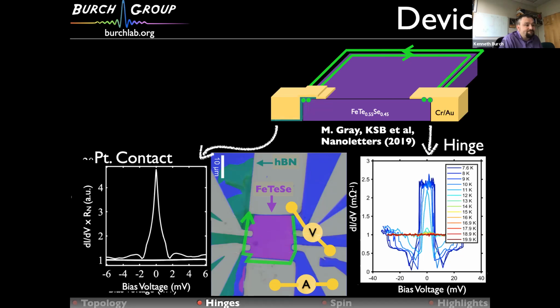But the temperature range is the same as before, right? Previously, the problem whenever you do these transport measurements is that if you don't wire your cryostat well, then you're actually carrying a lot of heat in. So you're not as cold as you think you are in your device, which we didn't know at the time. So we basically rewired the cryostat, long story short, with better thermal sinking. So it's actually somewhat colder, and also, frankly, the crystals are better. I mean, you can just see it by eye when you cleave them. They're bigger, flatter, beautiful, etc.